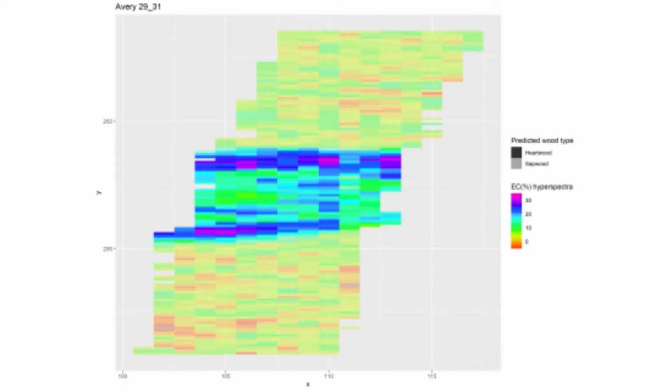These correlate to the chemistry of the wood, and we can do this spectroscopy assessment within seconds, non-destructively on wood. We take our cores from the trials, bring them to the lab, and then scan them with the infrared spectrometer, and we have calibrated it against our extractive content measurements, and we get quite accurate prediction of extractive content.